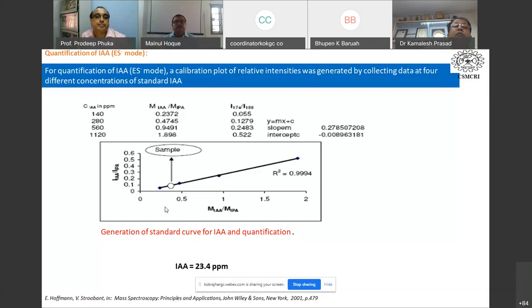So indole propionic acid we have used as an internal standard for detection of indole acetic acid. So again, similar to UV, we have to prepare a standard graph here. The standard graph just depends on the ratio of the intensity of indole acetic acid and indole propionic acid, and it is a mass ratio of indole acetic acid and indole propionic acid. So this is the ratio we got, and with the R square above 0.99, this is an excellent graph. When you get R square near to 1, you can consider the graph one of the best graphs for any quantification.